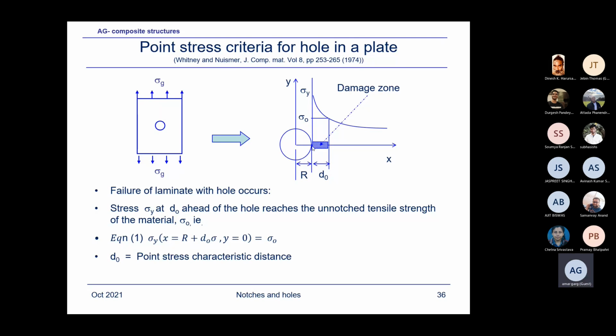Again, finally, the criterion is similar to this one. That's why I prefer this. And this is the popular point stress criterion, which is also based on the same principle: that near the notch or the hole tip, there's a damage zone developed when you are loading the coupon.